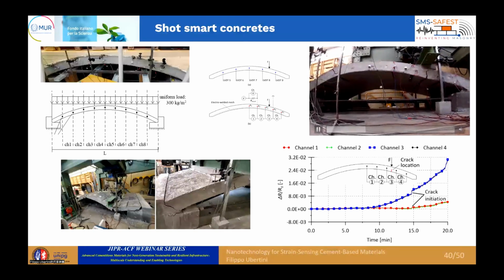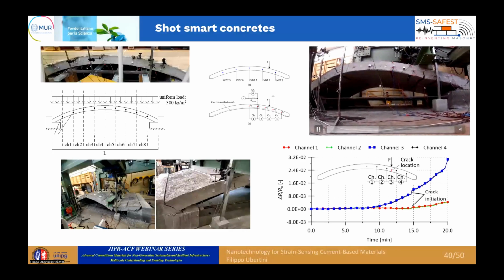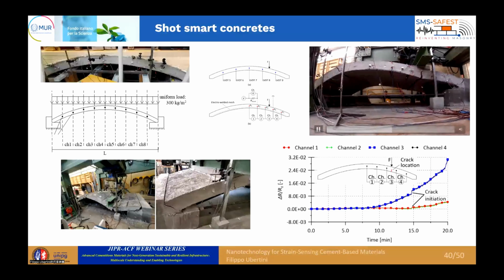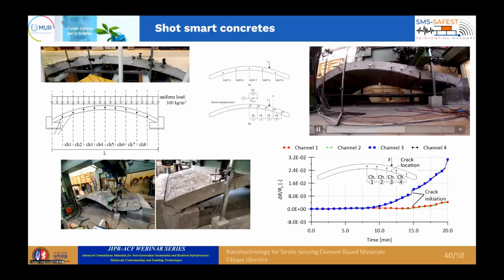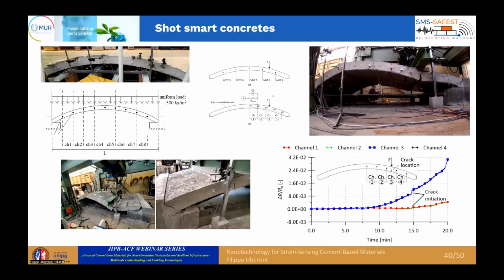You clearly see that we have a good ductility because we have a tie rod here, and so we are able to form a 4-hinge failure mechanism. And we were measuring with our smart material electrometer the voltage drops across the different pairs of electrodes all through the experiment. Here I'm showing you what we measured in the 4 channels in terms of relative change in resistance versus time during the test. You clearly see that as long as I was loading the vault, we show increases, depending on the channels, of course, of the relative change in resistance. In channel 3 and channel 4, which is where the crack is located, we see a clear jump when the crack started to initiate, and then we have an evolution of the relative change in resistance that increases with the applied load.